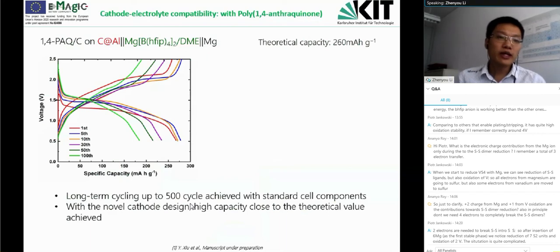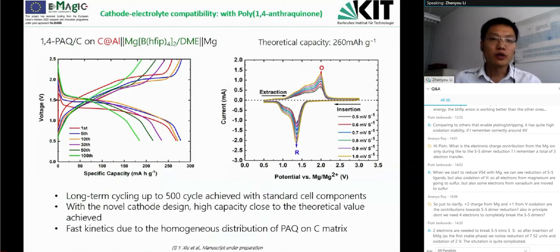So then we tested the battery performance using this new cathode design and also coupled with the borate electrolyte. And here we see basically we could run a cell for up to 500 cycles with the normal, or let's say standard, cell components, which indicates a good compatibility. Also, here we could achieve high capacity with the new cathode formulation, and this is close to or even exceeds the theoretic capacity a bit. And with the homogeneous distribution of the active material on the conductive carbon, we could also achieve fast kinetics, as demonstrated here in the CV with different scan rates.